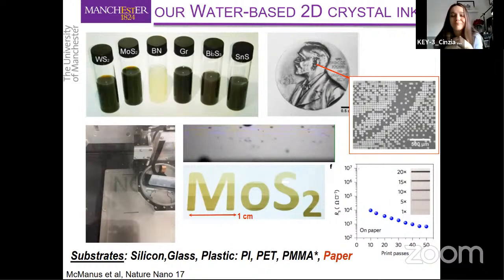And this is because we can print with a very small resolution. On paper, we can go down to 8-10 microns, which is well beyond the nominal resolution of the printer, which is 50 microns. But more important, when we print on paper, because of the porosity of the substrate, we can actually minimize the sheet resistance. So as you can see in this plot here, we can achieve a sheet resistance below 1 kilo ohm per square by printing just a few printing passes, so by printing on top of the same feature over and over. And this is achieved by printing under ambient conditions and without using any pre-processing or post-processing.